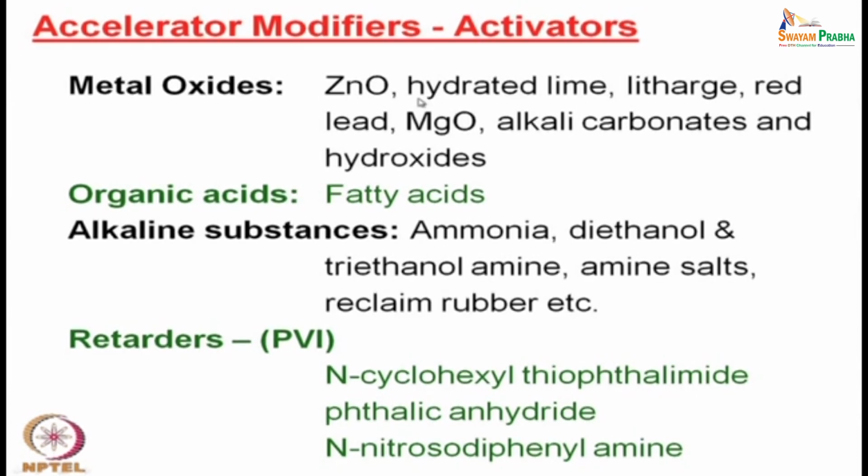In some cases hydrated lime, litharge, red lead, magnesium oxide, alkali carbonates, and some metal hydroxides can also be used. Basically these are alkaline or neutral materials. Zinc oxide is neutral or alkaline.